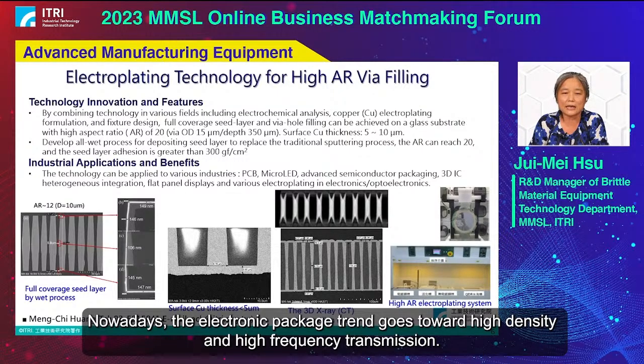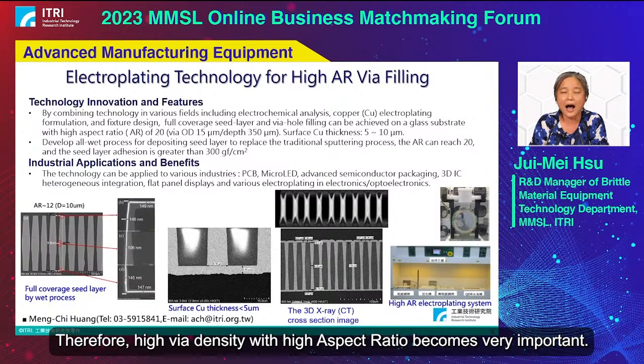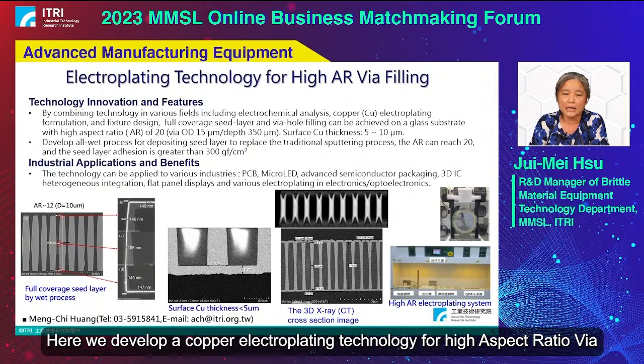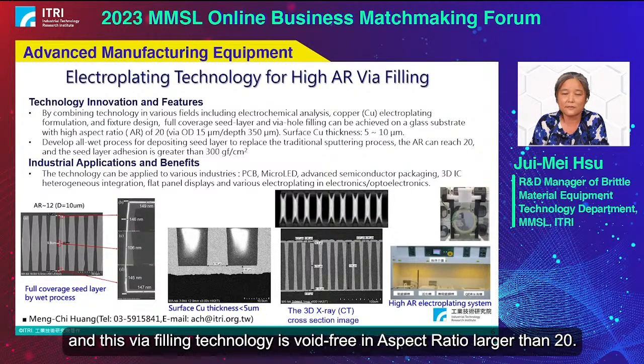Nowadays, the electronic package trend goes toward high density and high frequency transmission. Therefore, high via density with high aspect ratio becomes very important. Here, we develop a copper electroplating technology for high aspect ratio via. And this via filling technology is void-free in aspect ratio larger than 20.